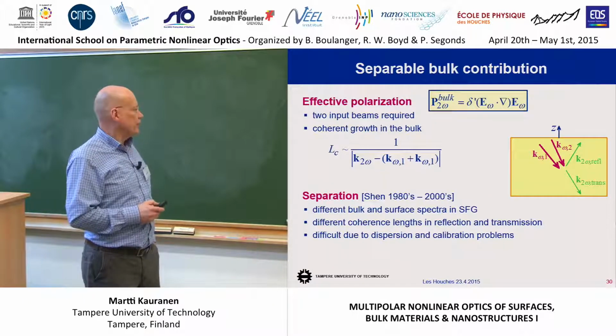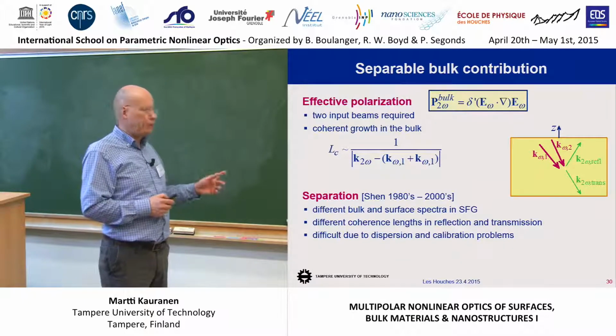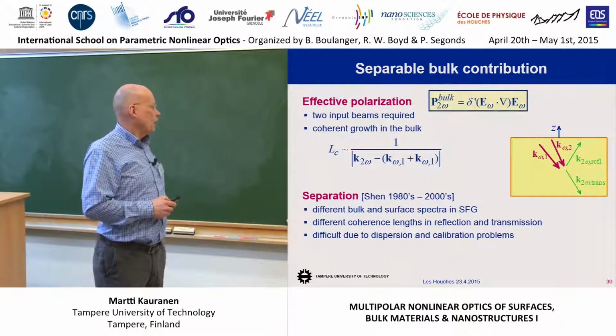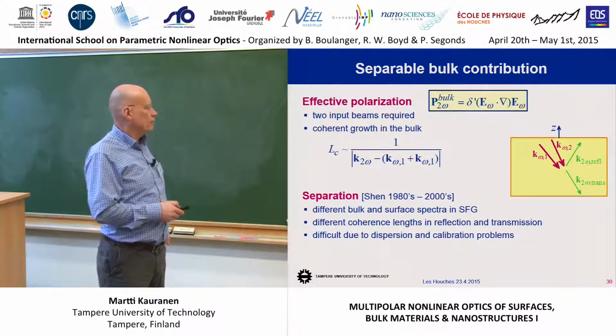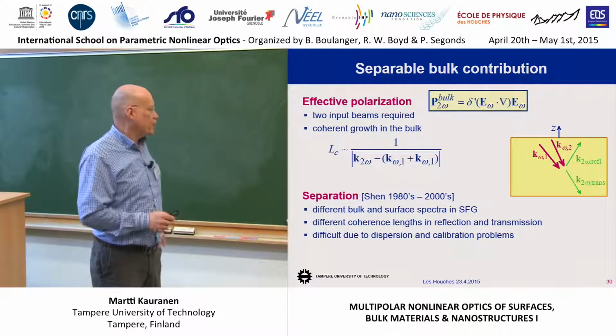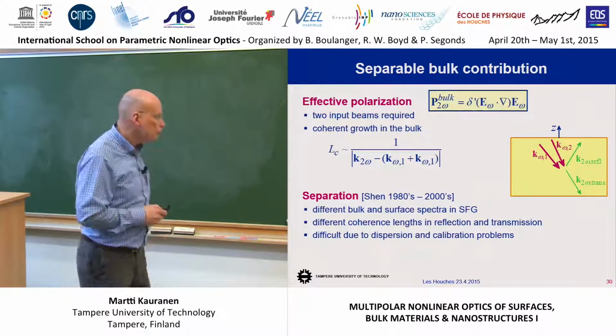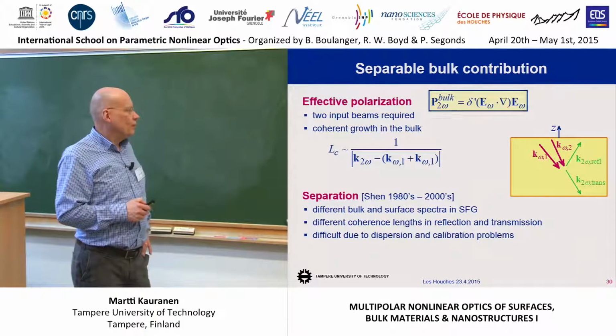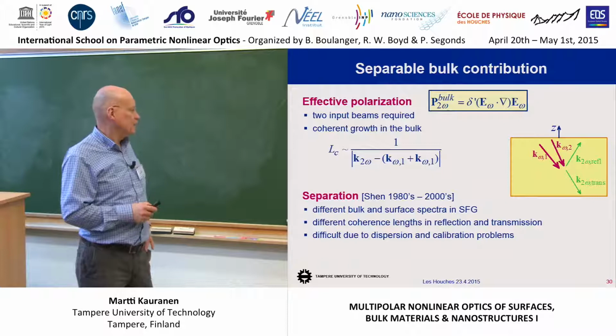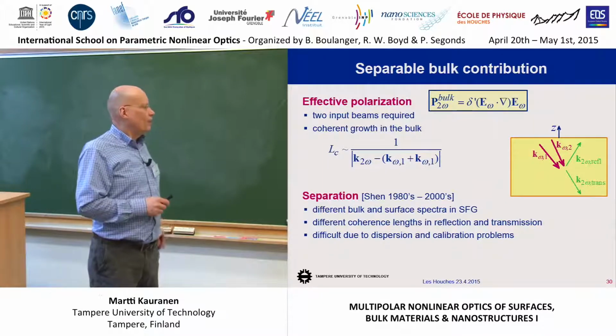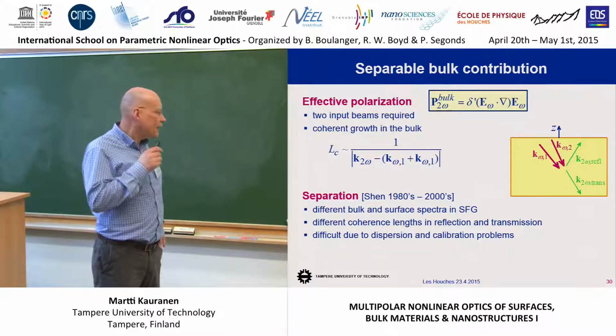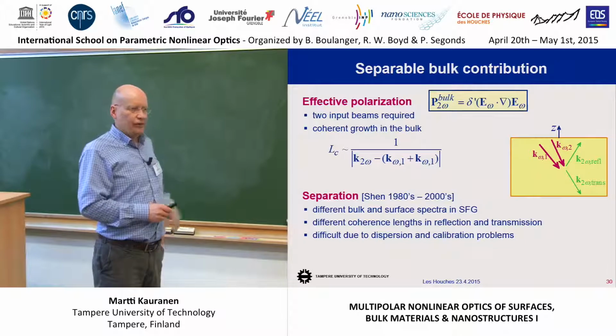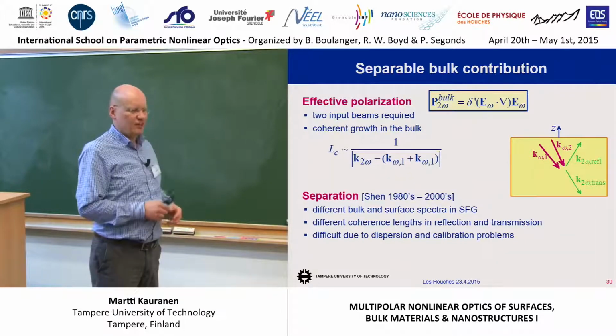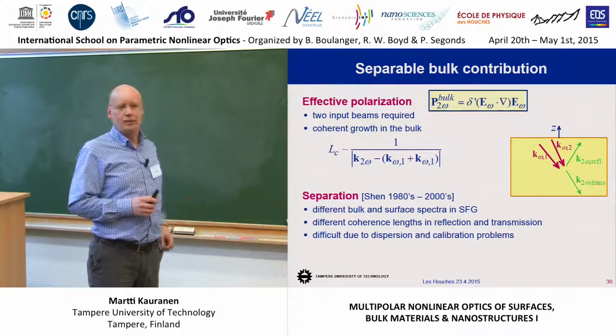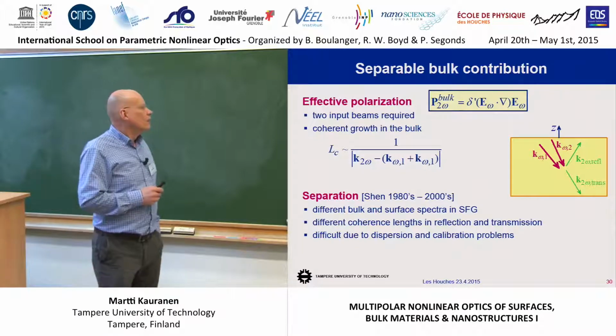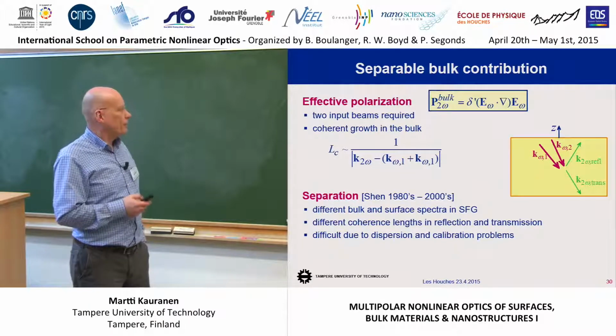So he did sum frequency generation, relying on the difference in the spectral response in the bulk and at the surface, trying to utilize the fact that the coherence lengths in reflection and transmission are different, and so on. But all these experiments had difficulties because of the material dispersion. And another thing is that if you do experiments, it's extremely difficult to calibrate absolute signal levels. So if you compare signal, let's say in transmission and reflection, and you want to calibrate them in an absolute sense, that's a painful process. So all kinds of things somehow hampered these experiments.